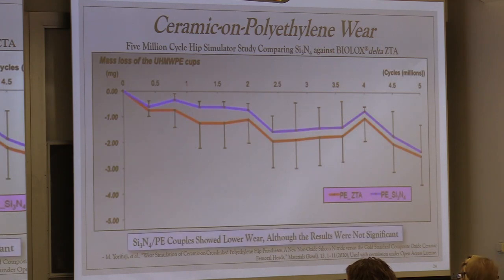And the second major area is, of course, wear and osteolysis. So this is my recent data, which, again, the FDA requires that you take a predicate material, in this case a zirconia toughened alumina, and in a hip simulator, you look at the wear of the device, and this is wear against ultra-high molecular weight polyethylene. And what you're seeing here is the lower curve, it means more wear, so that's greater loss of mass. The upper curve is lower loss of mass.